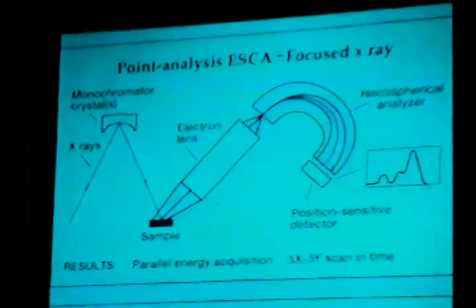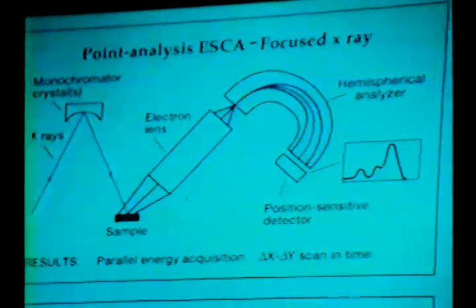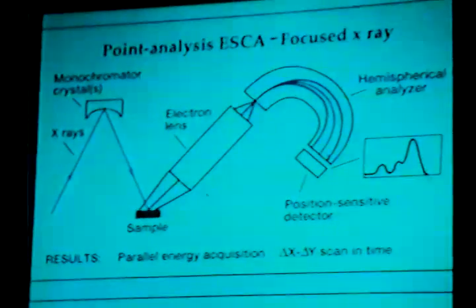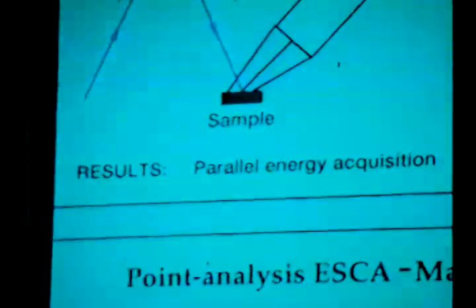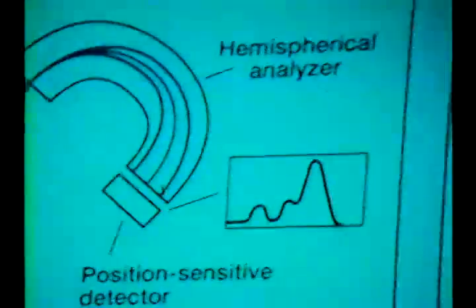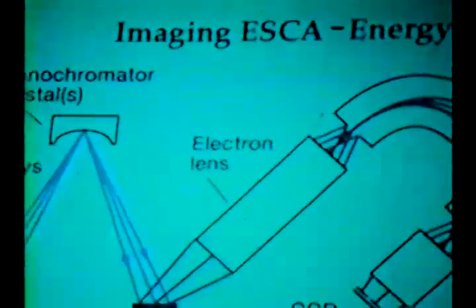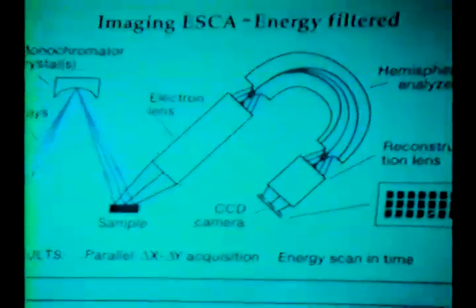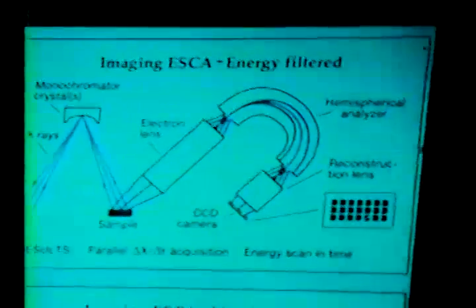If we use valence band electron spectroscopy and have a good theory, we can arrive at conclusions about modes of bonding. We study equilibria both experimentally and by thermodynamics. And the dynamics, or kinetics, the most important aspect of catalysis, deals not only with rates of adsorption and desorption, but also with control of catalytic selectivity through relative rates of different surface reactions. I'm going to give a few examples of how we analyze this palladium system.